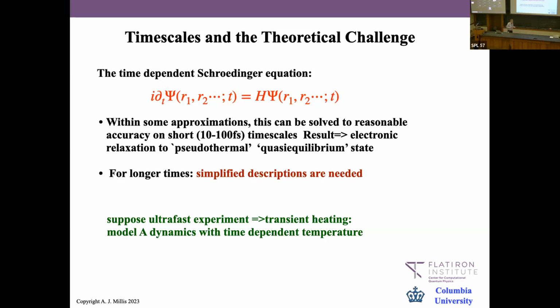So now one would like to think about these experiments, and the problem is that they're not at all amenable to direct computation. Basically, what you want to do in each of these cases is solve the Schrodinger equation starting from an initial condition and see what happens. What we can get to, as I'll show you a little later with some rather brutal approximations, is few to tens of femtosecond timescales, which is factors of 10 to 100 less than the timescales we're really talking about. So you need some way to connect the short times, which are computationally accessible, to the long times that you're interested in.